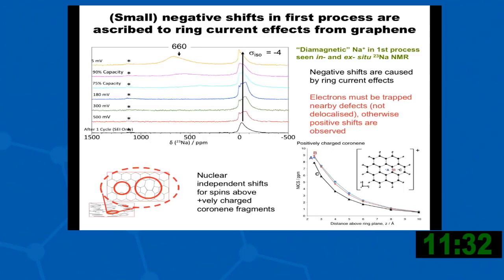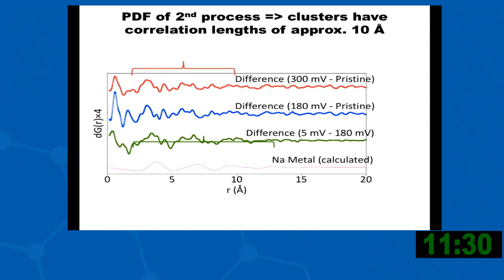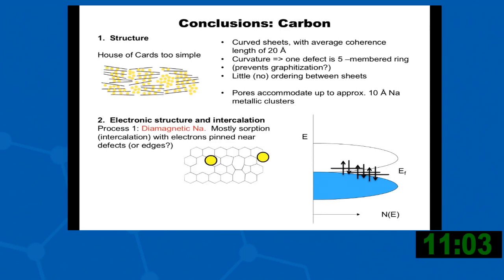And so we can put this all together now. This is now the PDF of the sodium in the hard carbon as a function of state of discharge. And when we're at 5 millivolts, we can see correlations, not beautiful, that are reminiscent of sodium metal. So this is the 300, 180, and 5 millivolts, and this is the difference between the pristine and the low voltage, and you can see at least correlations that say something about little sodium clusters in the system.